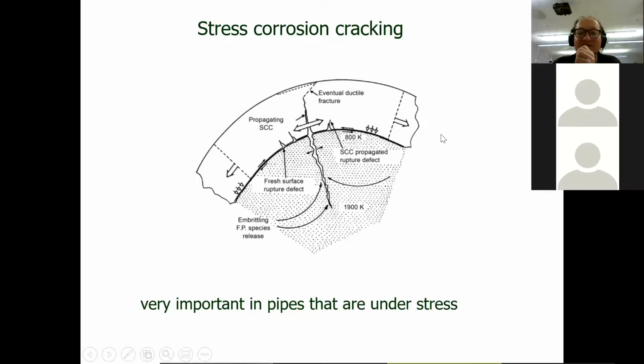And the only reason that it doesn't is because it's designed so that the wall thickness and the strength of the material should be able to withstand the force or the pressure inside it. And that's normally okay, up until the point you start to get these defects forming here. And once you reach that point, then you're almost certainly going to have a failure at some point. Simply a question of waiting long enough for it to happen. It might be years, it might be 20 years or so, but you can be sure it will eventually break.